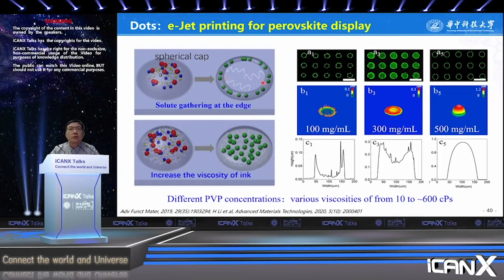Reducing the solute movement rate can reduce the coffee ring. One of the effective ways is to increase the viscosity. However, it makes inkjet printing more difficult, and even makes the nozzle clogged. So it is seldom used in traditional inkjet printing, but it's totally different in EHD printing.